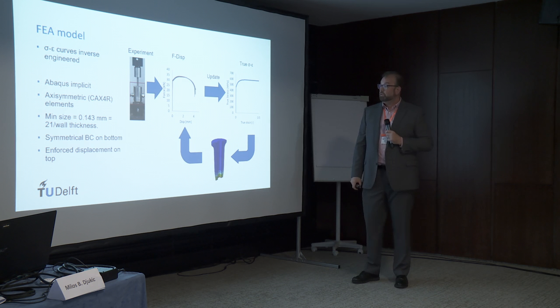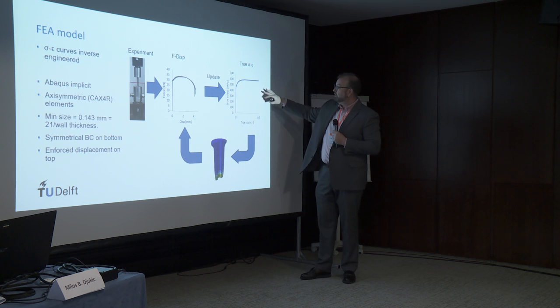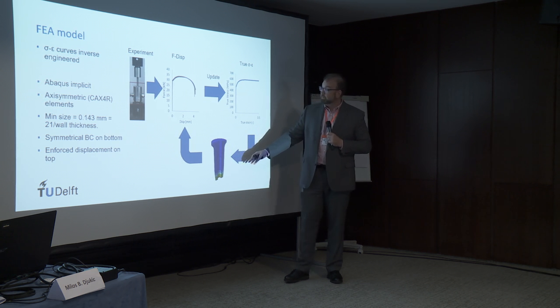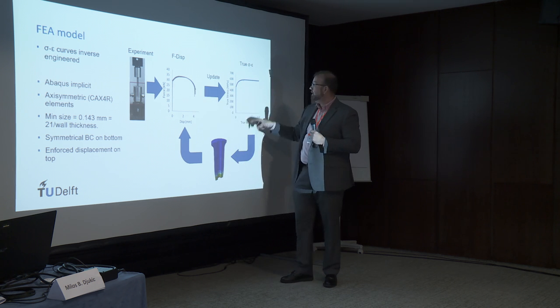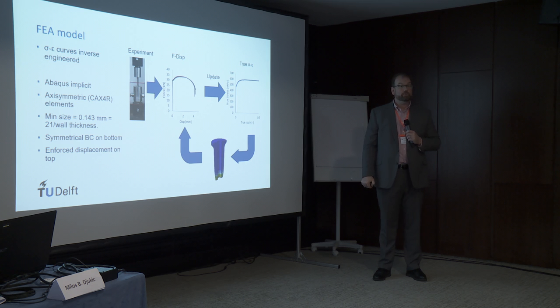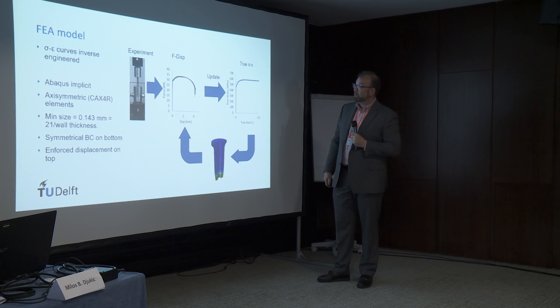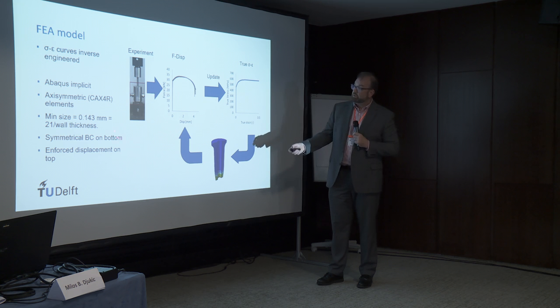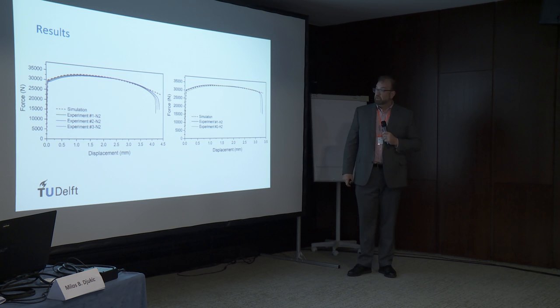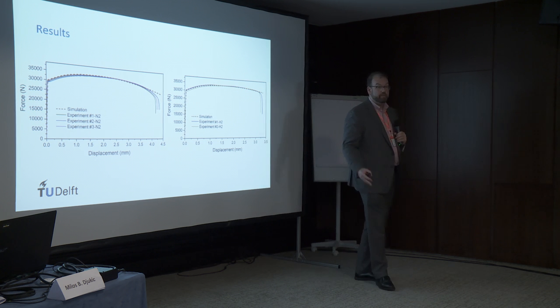How do we interpret this? First, we have a force-displacement curve from the experiment. We hypothesize a true stress-strain curve, substitute that into a finite element model, post-process the finite element as if it's an experiment, compare that to the experiment, and then iterate until it works. This is a fairly common procedure recognizable to anyone who has done damage mechanics calculations. In our case, this iterative process was done through an optimization algorithm.